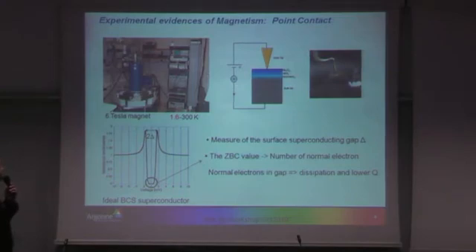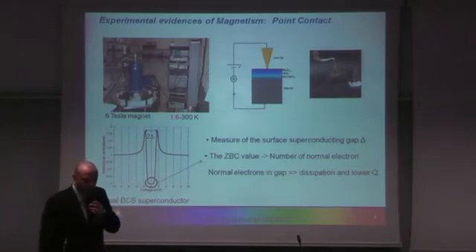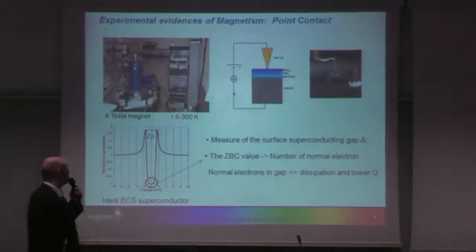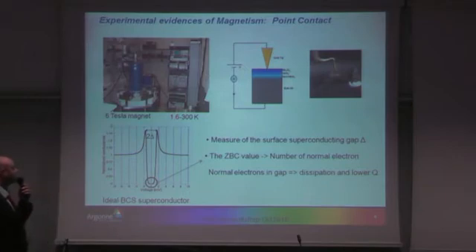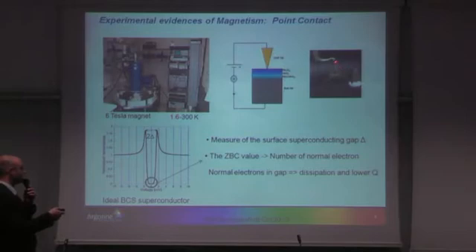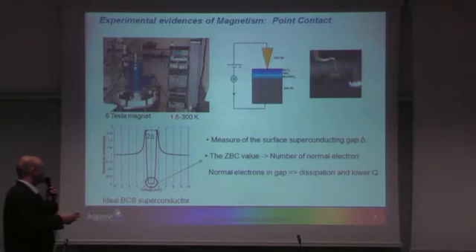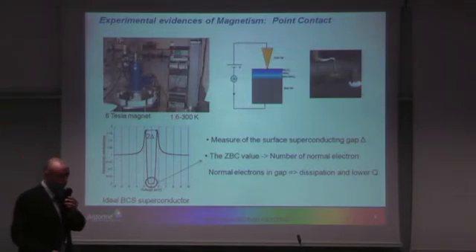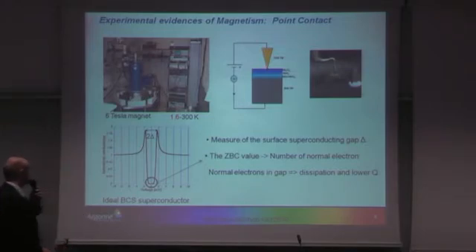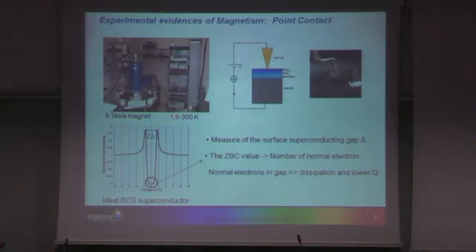We started with point contact tunneling spectroscopy. You apply a voltage between a gold tip that comes into contact with the niobium surface. The gold tip is here, and you use the insulating oxide as a tunnel barrier, so the potential drops there. You sweep the voltage and measure the current, giving an IV characteristic, or a dI/dV if you measure the derivative via a lock-in.